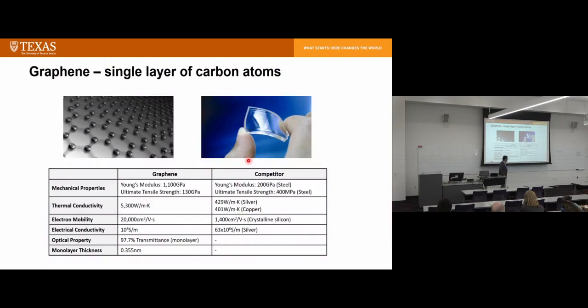As you probably know, graphene is a single layer of carbon atoms. It has been touted as a wonder material with a lot of applications. If you look at the property comparison between graphene and competitors: Young's modulus is 1,100 gigapascal, and ultimate tensile strength is 130 gigapascal. Thermal conductivity is 5,300 watt per meter Kelvin. Electron mobility is 20,000 centimeter square per volt second. Conductivity is 10 to the 8th Siemens per meter. Optical transparency is 97.7 percent for monolayer. And thickness is very thin, 0.355 nanometers, because it is one layer of atoms.